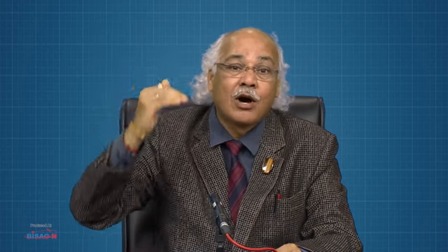The rebound hammer is a current practice, like a stethoscope of the doctor. Of course, many persons have differences of opinion, saying it is not a trustworthy instrument. But from my angle, the rebound hammer test is trustworthy when you mix your experience with the result of the test. It is a very trustworthy instrument. It requires an average, particularly for a column. There are 4 faces, and we have to select the 4 faces. Randomly, it may be at 1 meter height, or 1.20 meter height, or 1.50 meter height, or 1.75 meter height. You have to take nearby 9 results, 9 rebound hammer tests.